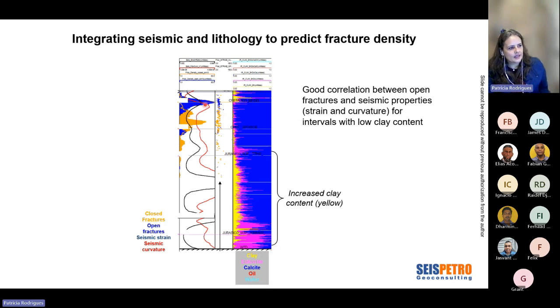We can see that there is a good correlation if you look only at the first part of the reservoir: when you had more strain and more curvature, you have more open fractures, which is the blue here. Where you have less, you have only closed fractures. But of course, after this section, there is no correlation. You actually have more deformation here and there are no fractures. That's due to the increase in clay content, which is the yellow. If you have ductile material, the fractures won't develop, even if you have the deformation.